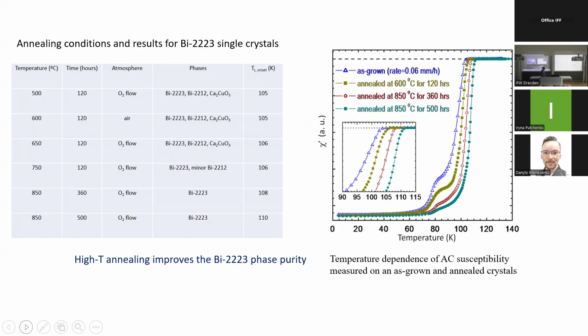If we look at the magnetization curves, still there is the small kink at 80K. But the amount of bismuth 2212 impurities was estimated to be around 1 weight% only. But still, we are not able to prepare impurity-free bismuth 2223 samples. We always get bismuth 2212 intergrowth defects.